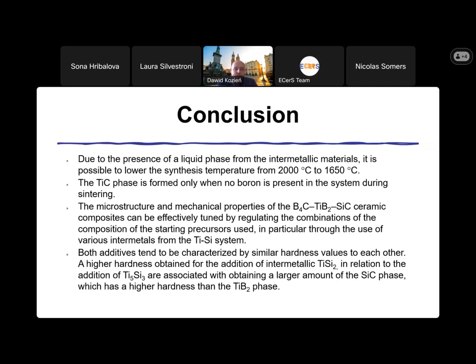Both additives tend to be characterized by similar hardness values to each other. A higher hardness is obtained for the addition of intermetallic titanium disilicide. It's obvious because we have more silicon carbide. In relation to the addition of Ti5Si3, we obtain, as I say, more silicon carbide, which has a higher hardness than titanium diboride.